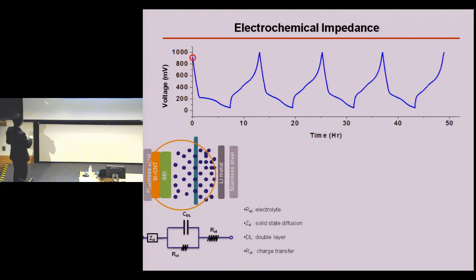So this is the equivalent circuit for this kind of transport study. You can see here, this is the component from the lithium transport across this structure. And this is the double layer related impedance. And this is the charge transport at the interface. So luckily, all these components will show up at different frequencies. Because for this part, lithium ions can transport much faster in this layer compared with in the silicon carbon nanotube layer. So this impedance will show up at the high frequency.